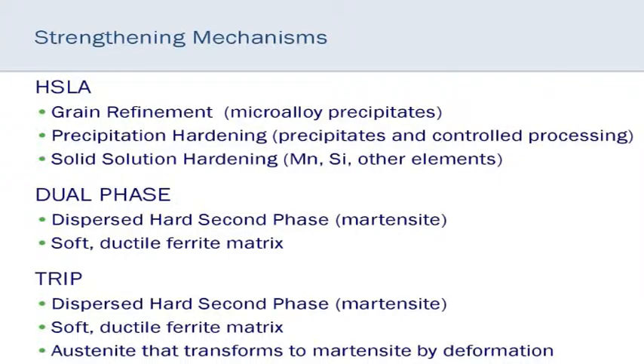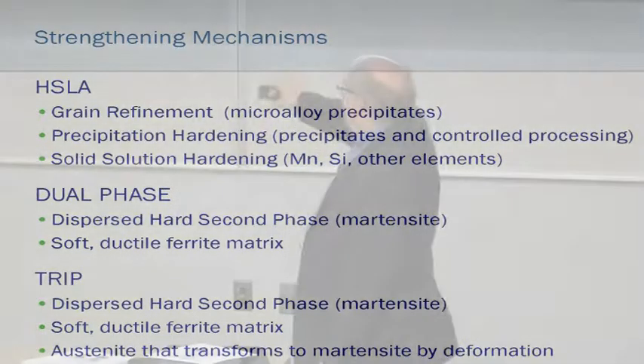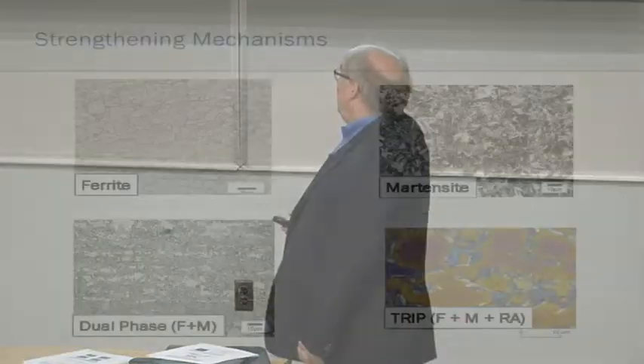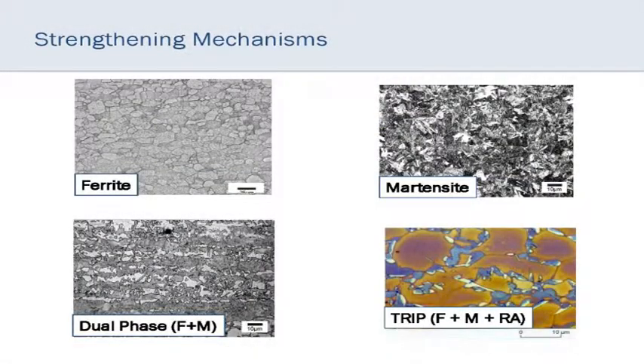And the TRIP steels, or transformation-induced plasticity, introduced the austenite, and austenite is a very unstable microconstituent. So as you form it and add strain to the microstructure, that austenite transforms, or trips, into martensite. So it's formable as austenite, but when it trips into martensite, it's very strong, so it gives you the best of both worlds.